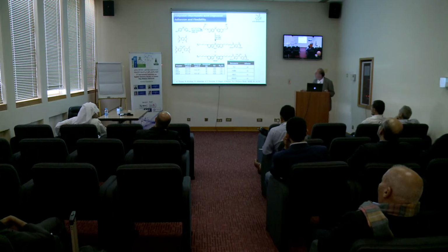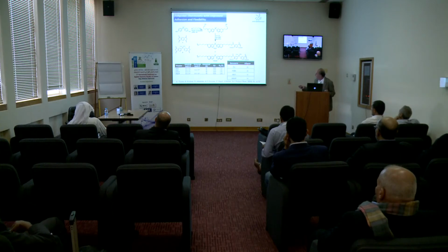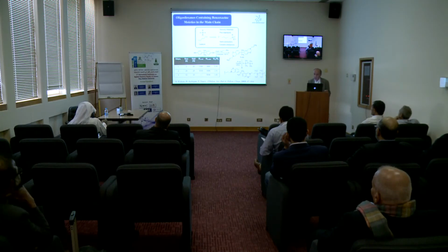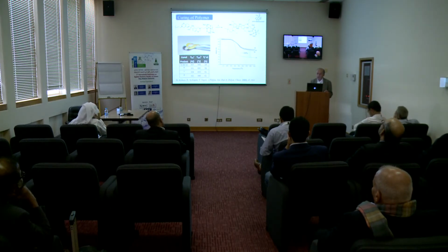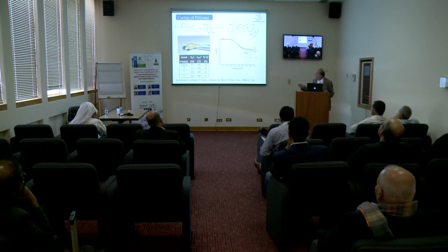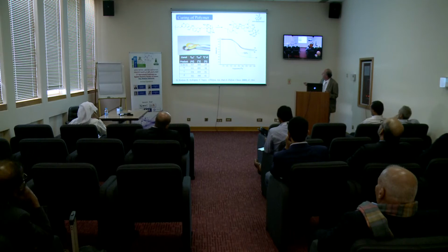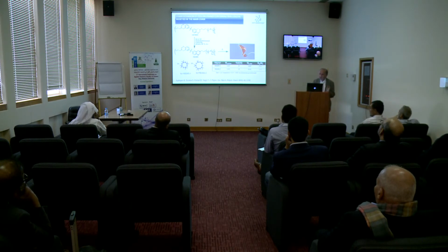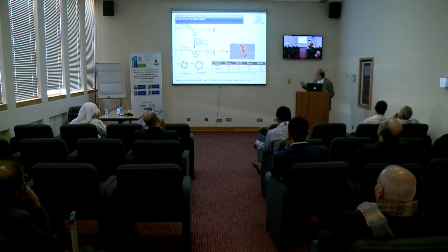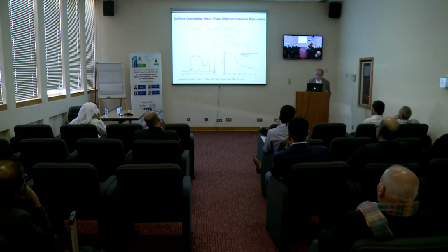So we were able to increase the adhesion on the surface by attaching carboxylic acid groups here. As you see, the normal benzoxazine adhesion is very low, increased when the carboxylic acids are present there. And we went the way of more flexibility by taking advantage of polysiloxanes. As you see here, the polysiloxane is a flexible material, and the thermal stability is really very high, even at 800, 900 degrees, some percentage remains there. If you increase the siloxane unit, you can twist the material, it's extremely flexible.